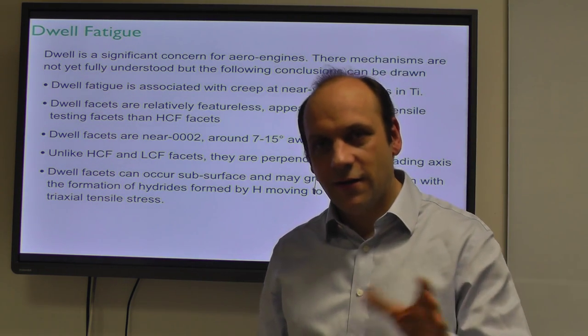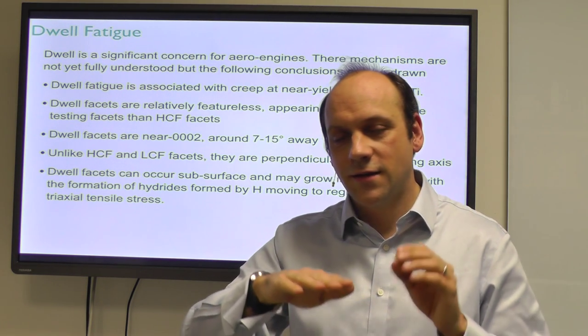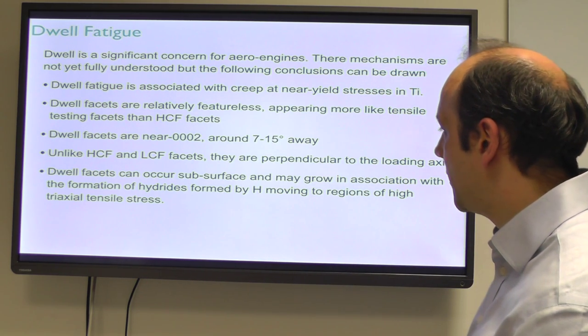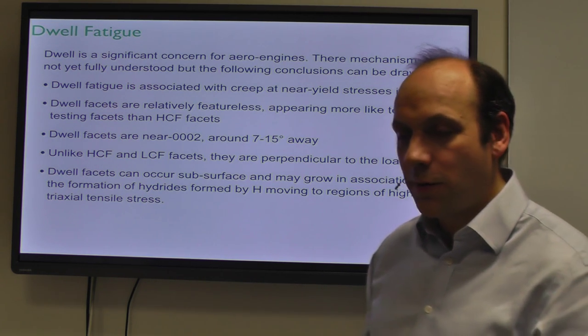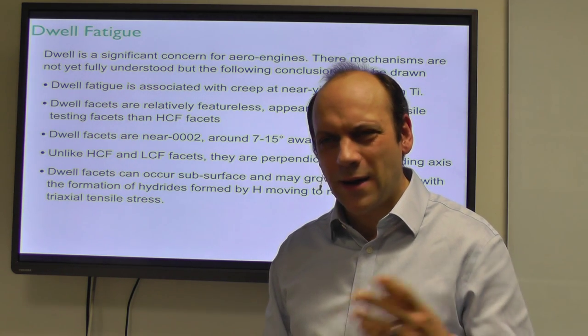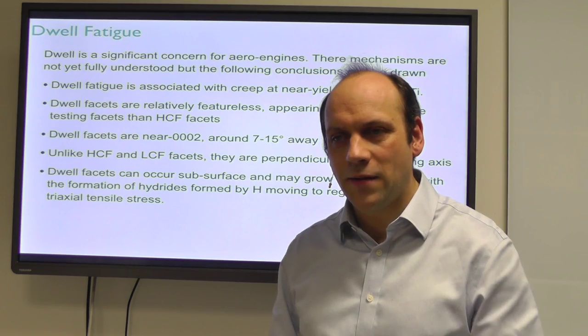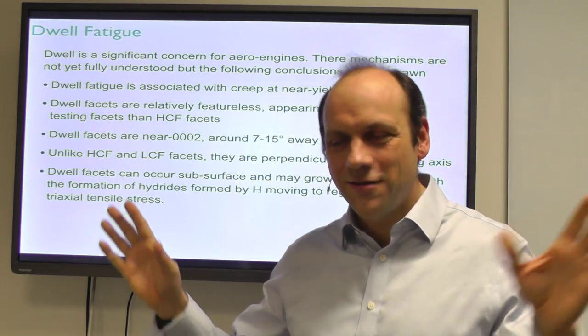Unlike HCF and LCF facets, which tend to be inclined, they're perpendicular to the loading axis, so that's why we invoke the Stroh mechanism. Dwell facets tend to be subsurface, and they may grow in association with hydrides or with hydrogen, we don't know which. It may be that hydrogen moves to the regions of high triaxial tensile stress, and then when the facet goes, they precipitate out. We don't know. There are some indications on fracture surfaces, but we don't really know.